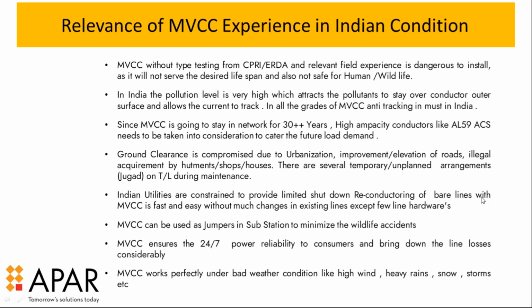Then we have also seen that installation time is very fast and easy in the case of covered conductors, and utilities are always reluctant to give you shutdowns while you are reconducting the line. If they are already supplying the network to some distribution line with the bare line, and you are reconducting it, they will not give you all the clearances very fast, or the shutdown time is very little. So in the case of the covered conductor, this reconducting can be done very easily without wasting much time.